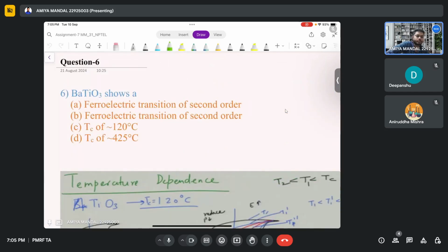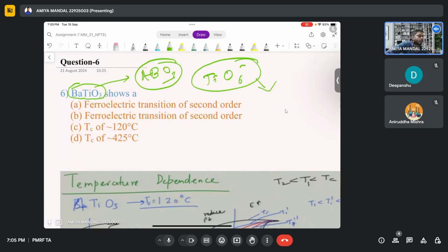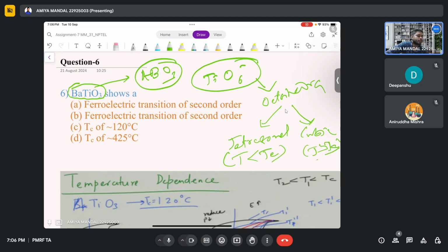Question number 6. Barium titanate. This is also a ferroelectric material, a perovskite material with an ABO3 structure, where titanium sits in the octahedra. It shows two types of variation, tetragonal and cubic, for T less than Tc and T greater than Tc. Tc here is 120 degrees centigrade. These are some basic information about barium titanate. So barium titanate is a ferroelectric material.